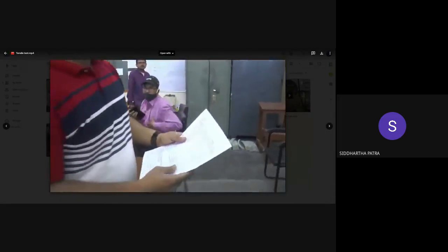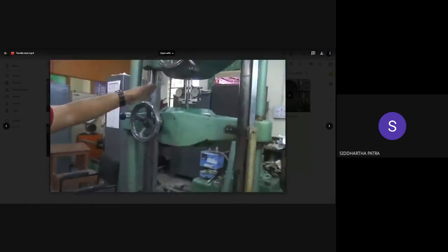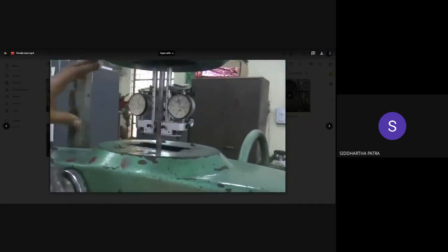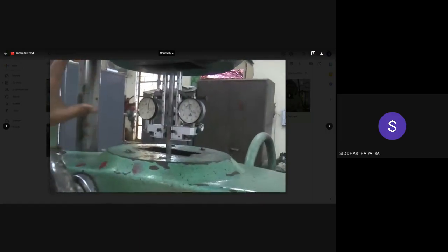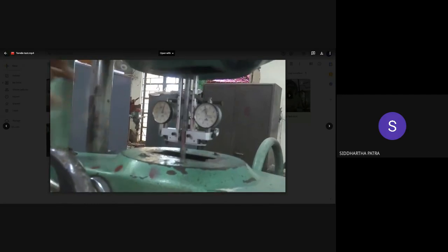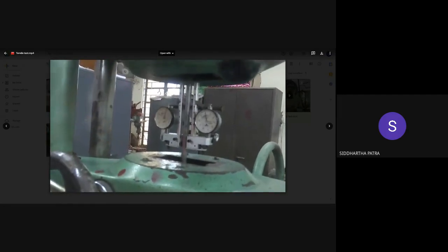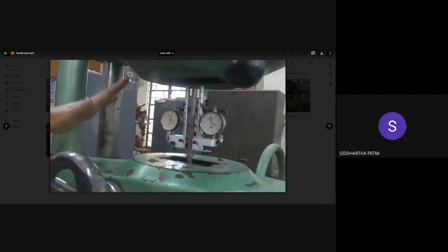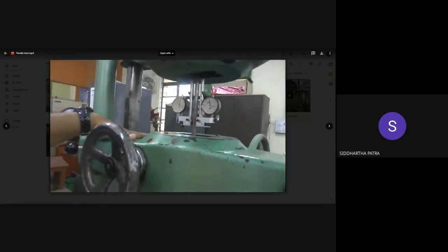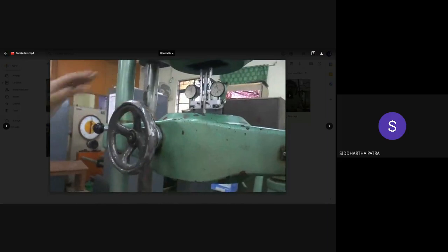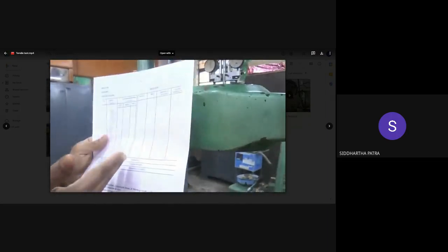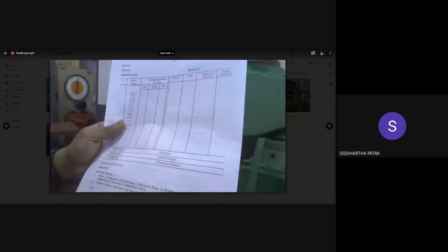So now the thing is, we don't want our extensometer, which is a very delicate instrument, to be subjected to plastic deformation. So we only want to use this extensometer up to the yield point. This instrument is there only for measuring the elastic strain. Once we know we have hit the yield point, we will remove the extensometer, and beyond the yield point we are not taking any measurement of the strain. We cannot, because we have already removed the extensometer.